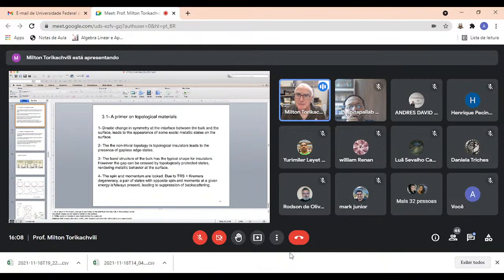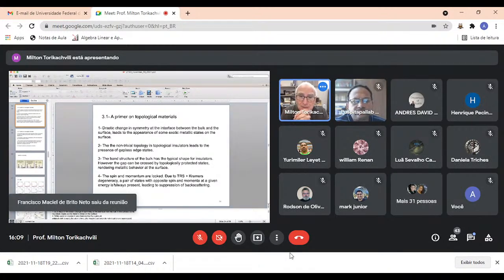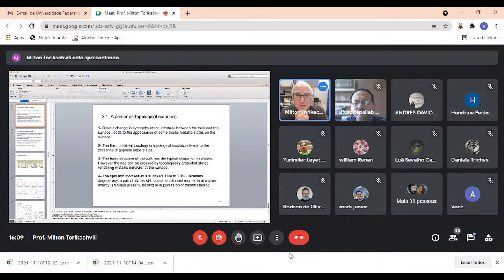A very summarized primer about topological materials. There's a drastic change in symmetry at the interface between the bulk and the surface, and that leads to the appearance of some really exotic electronic states at the surface. This non-trivial topology doesn't exclude, for example, the presence of gapless edge states, therefore leading to a more conducting behavior. The band structure of the bulk is typical of insulators, with a gap. However, that gap can be crossed by these topologically protected states. In these topologically protected states, the spin and the momentum are locked.